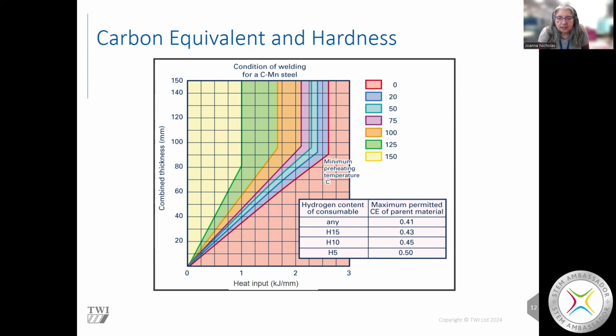And so this diagram is taken from a European standard, which tells us how to weld successfully without getting cracking, based on that work from the 1960s. You can see we've got lots of nice straight lines and a prediction table that says if I've got a particular combined thickness and a particular heat input, and I know how much carbon equivalent and how much hydrogen is there, I can predict what preheat I need. The standard includes about 20 of these images for different combinations of hydrogen and carbon equivalent. The reality is a little bit different.